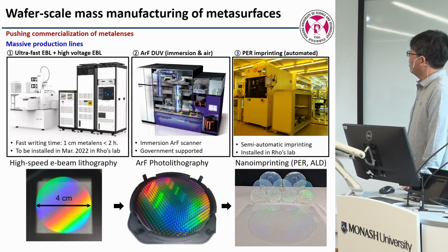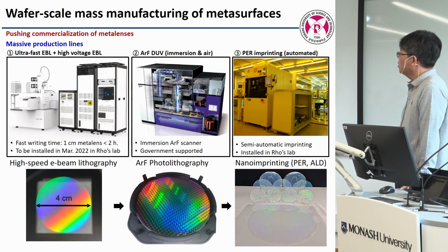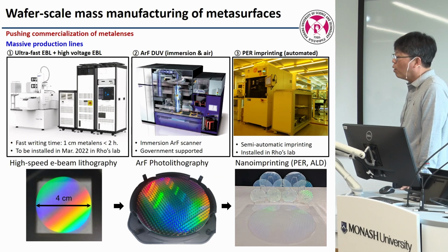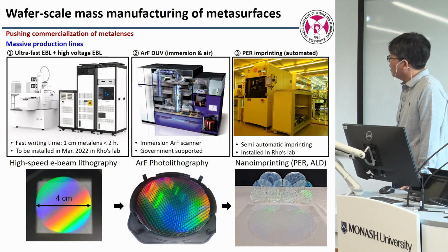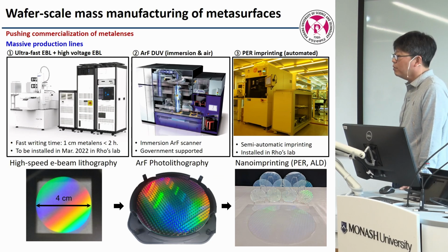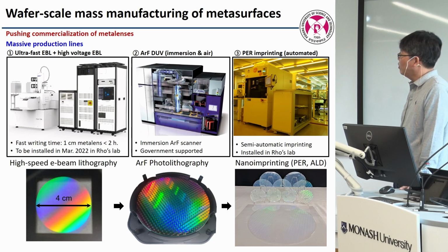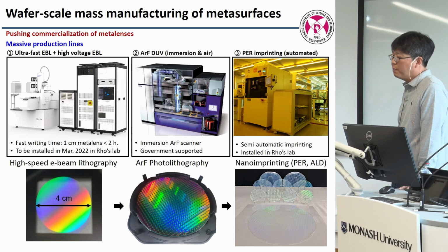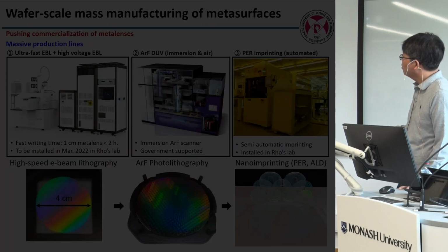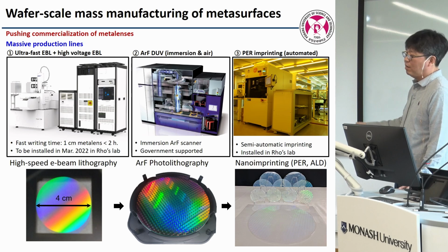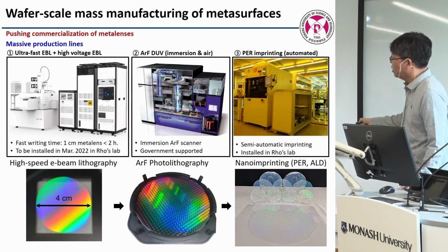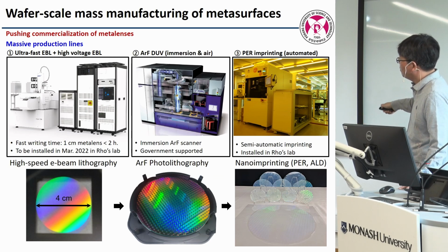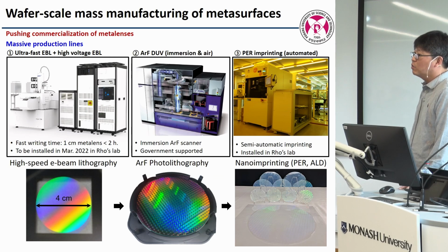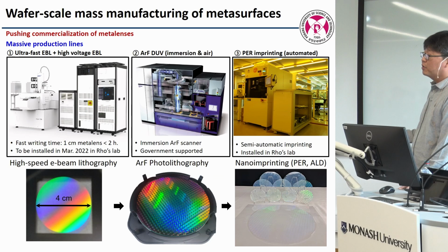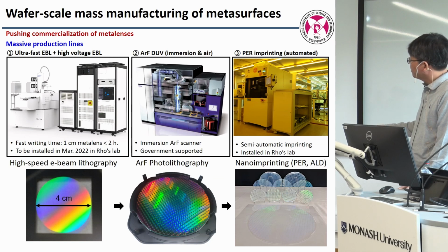And the last few slides are about patterning. It's a combination starting with e-beam lithography. Obviously we cannot avoid that because of the nanoscale pattern. So we make this e-beam original pattern as large as possible. Usually this is the last step: we experiment, and that's it, publish a paper. But now this original pattern is translated to the mask of the photolithography. Photolithography is a mass manufacturing tool, so we can do stepping with many repetitions, making the same device repeatedly on an 8-inch or 12-inch wafer. You can stop here. The semiconductor industry stops here, dicing, and this is your 600 metal lenses.